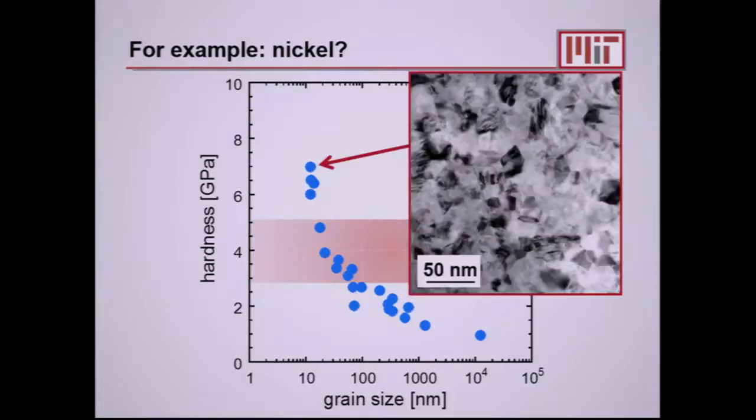And these are beautiful materials, right? So here is a typical electroplated nickel. This is from my lab when I first got to MIT. The purity is quite high. It's 3 nines or better. It's full density. It's very fine grains, and it's very strong.